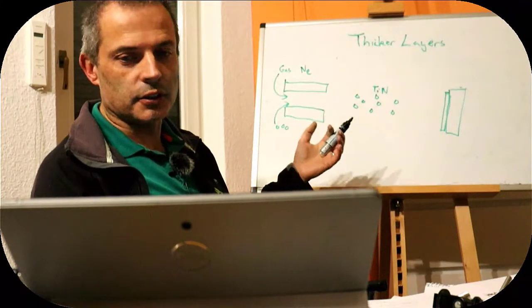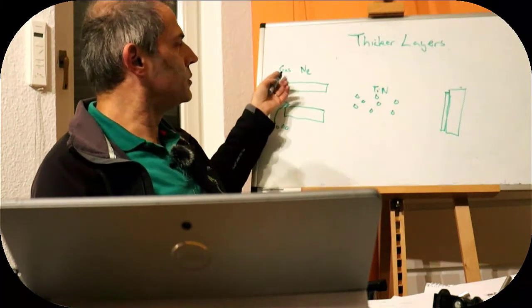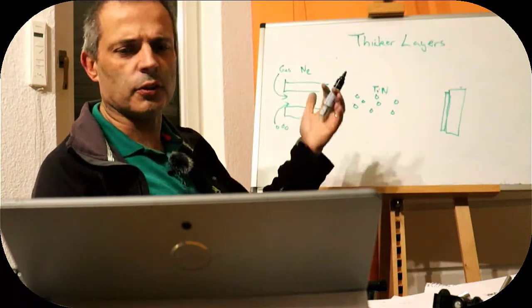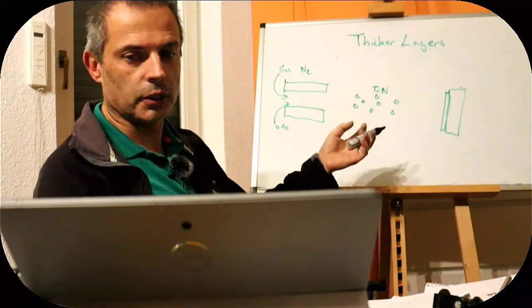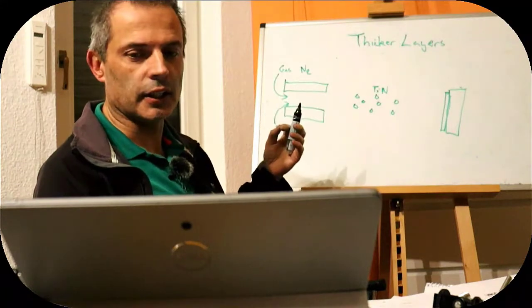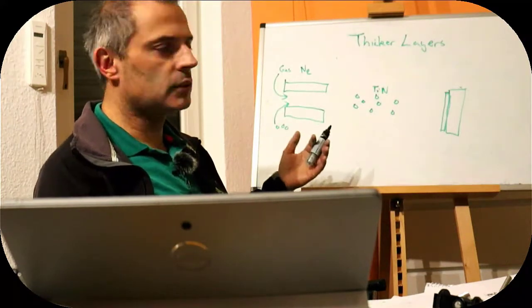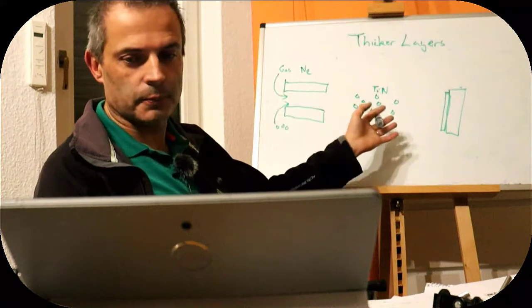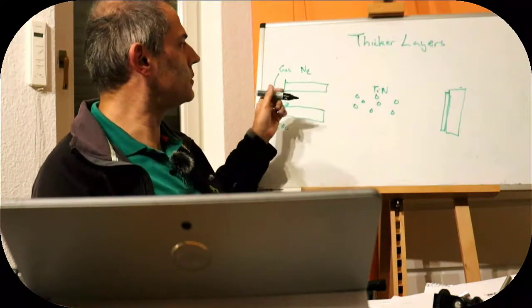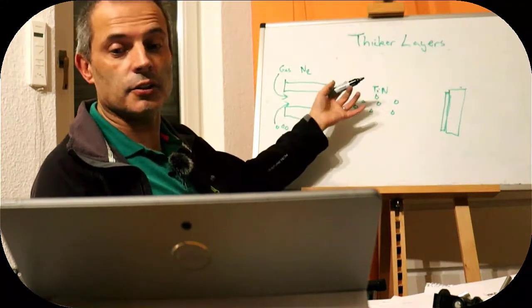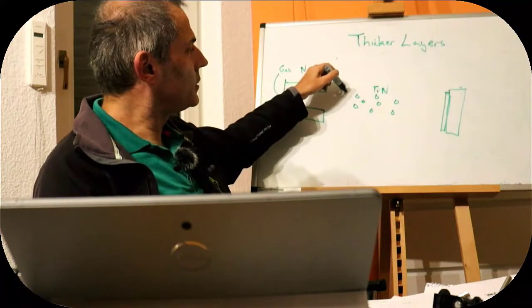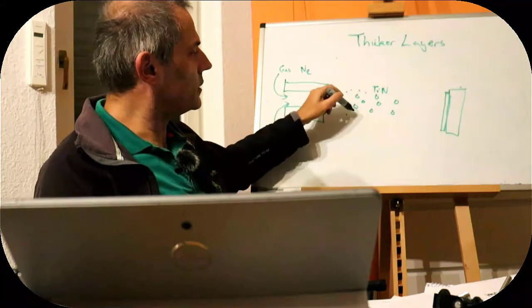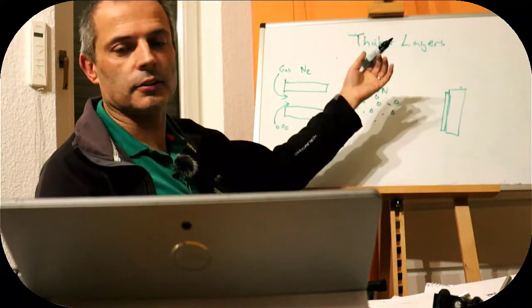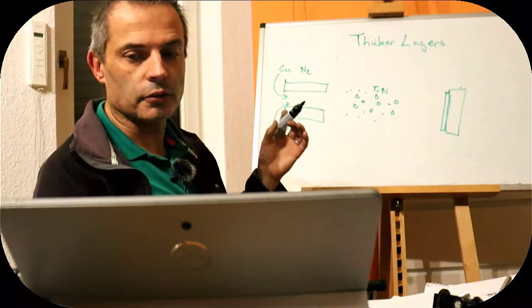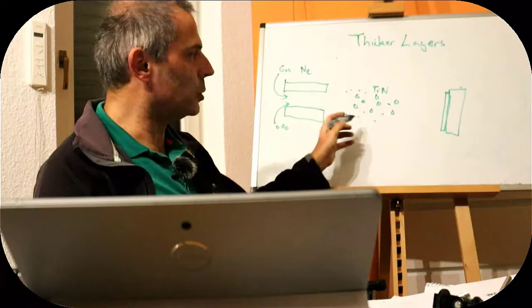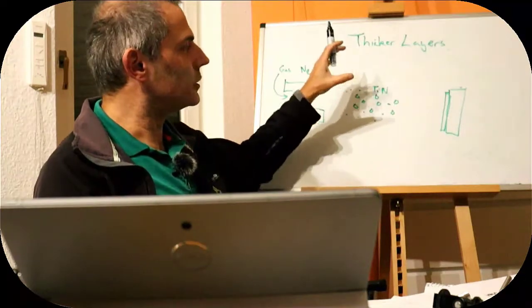and they only have the time of dwell inside there to get hot, and so we've got a problem of the two things not agreeing with each other very well. It's hard to get the heat in while having the speed, and the other problem is obviously that when we get out to here, if it's hot, the gas is going to be quite rare. If we're at 2000 degrees, there aren't a lot of gas molecules in the bit that's containing our titanium nitride.